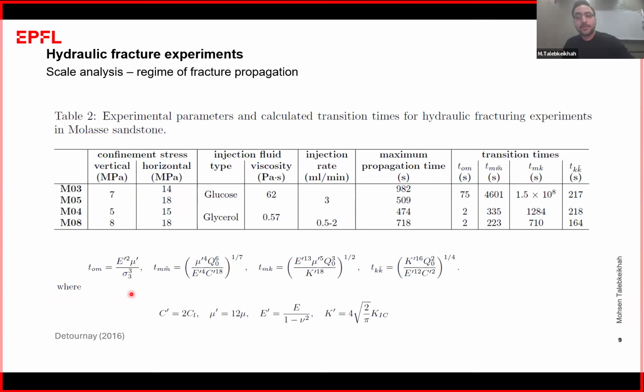So we were able to successfully do 4 different experiments. Their names are M03 and M05, in which we injected glucose with a viscosity of 62 Pascal second, and also M04 and M08, in which we injected glycerol with a viscosity of 0.5 Pascal second. After doing some scale analysis, whose equations are here, we could easily understand that in M03 and M05, where we injected glucose, the fracture regime is a storage viscosity dominated regime. And in M04 and M08, where we injected glycerol, the regime of fracture propagation was somewhat viscosity leak-off dominated, and mostly leak-off dominated.